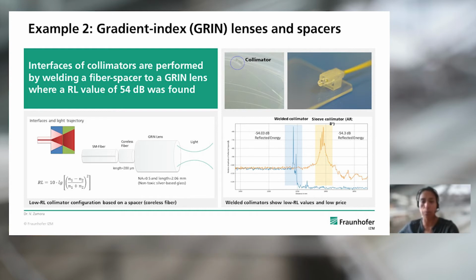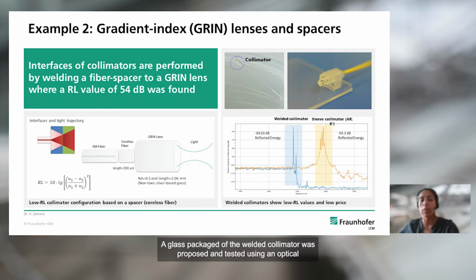By playing with the material, refractive index, and length of the coreless fiber, the return loss can be drastically reduced down to 60 decibels. The connection consists of splicing the coreless fiber and the standard single-mode fiber, and then welding the hybrid fiber to the GRIN lens. A glass packaged welded collimator was proposed and tested using an optical backscatter reflectometer. A value of 54 decibels was found and compared with that obtained using a commercial AR-coated collimator. Here we can say that the results are satisfactory as the welded collimator can additionally offer a permanent and low-cost connection.